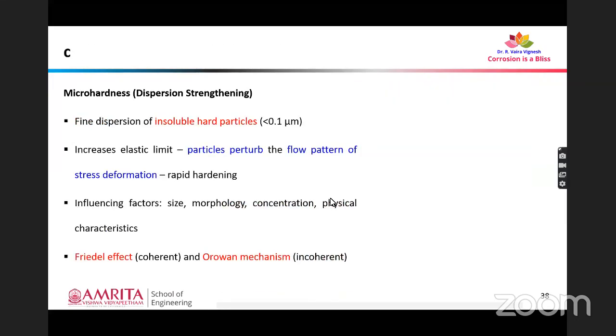Most composites will have an incoherent interface only. Why? Because we introduce ceramic phases into the metal matrix. The lattice of the ceramic phases will be completely different from that of the metal, right? So generally, these composites will have incoherent interfaces, so there is no matching of interface at all. So how do we get a strengthening effect? That is explained based on the concept of the Friedel effect and the Orowan mechanism.